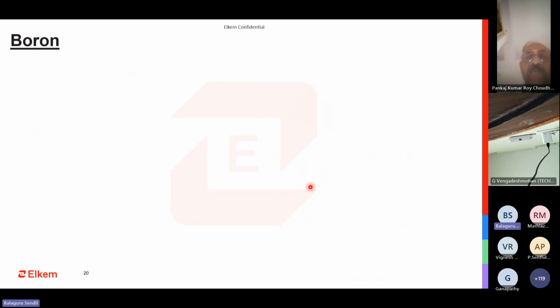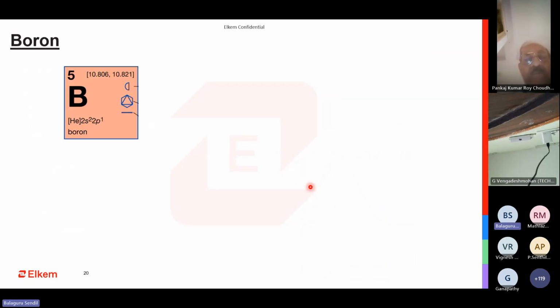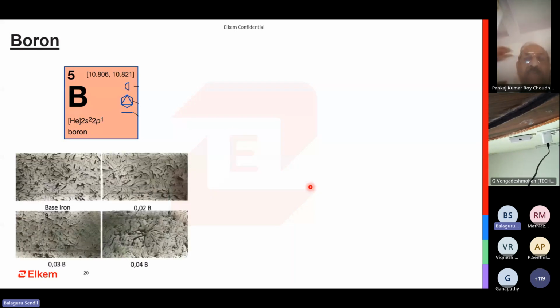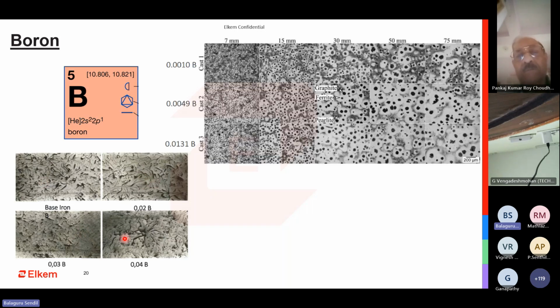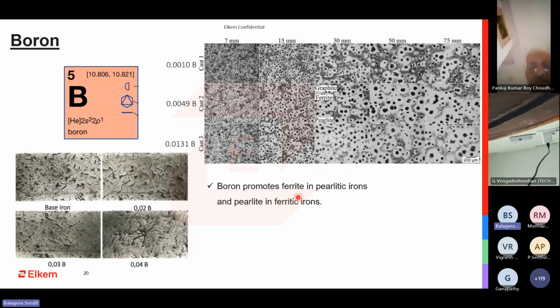Okay, this is quite an important and significant element, boron. Boron is also something steel people are allowing in. For base iron in a gray iron microstructure, boron is there, but not a very significant impact. But in ductile iron, we have different conditions of 7 mm, 15 mm, 30 mm, 50 and 75, and boron of 0.001, 0.005, and 0.013. If I compare the 7 mm from the first and the last one, it makes this look more pearlitic, and this look more ferritic. That's what it does. Boron promotes ferrite in pearlitic irons and pearlite in ferritic irons.